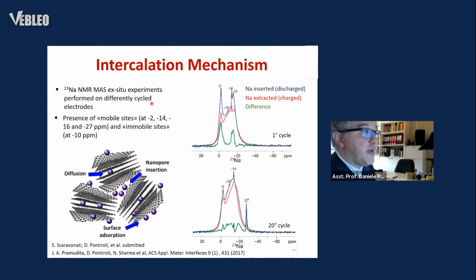The sodium intercalation mechanism in TiGO-based electrodes has been investigated also with NMR measurements in magic angle-spinning configuration on the sodium nuclei, performed ex situ on differently cycled electrodes. The spectra show the presence of either mobile or immobile sites ascribed to sodium ions, which are intercalated or deintercalated during the battery discharge or charging. And on the other hand, the sodium ions trapped in the solid electrolyte interface.